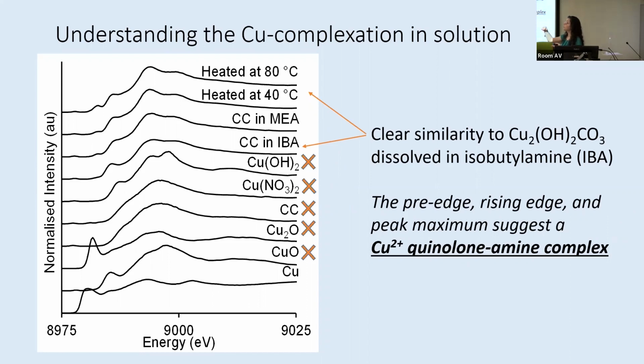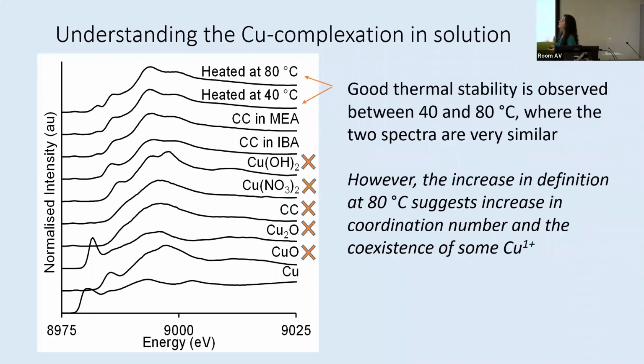And this has provided us a really important set of information, because as we unpick this spectrum, which you can see is quite complex, we can actually start to see that it looks like a quinolone amine complex, which is quite an appealing structure in terms of being aware of it. It's quite large. And so what we start to think about is the fact that, in fact, even with heating, we can still see this.